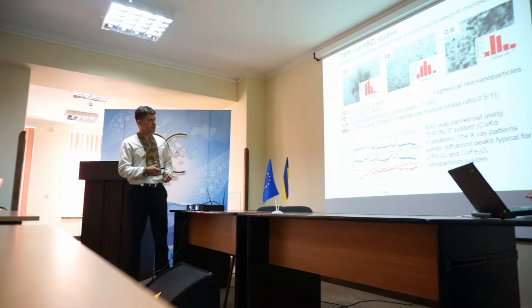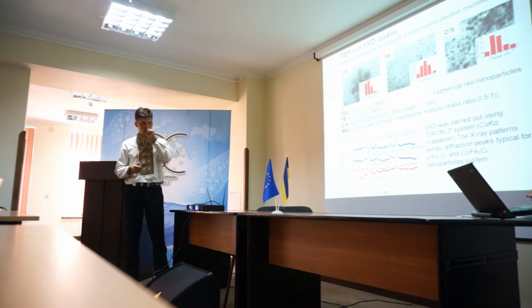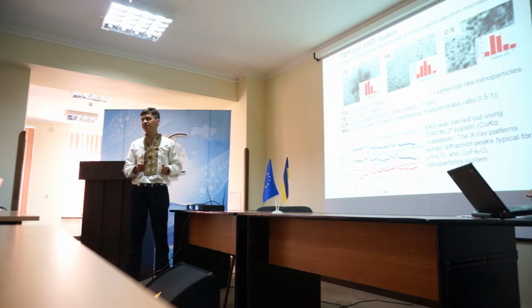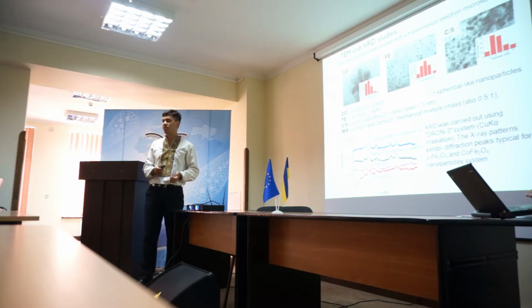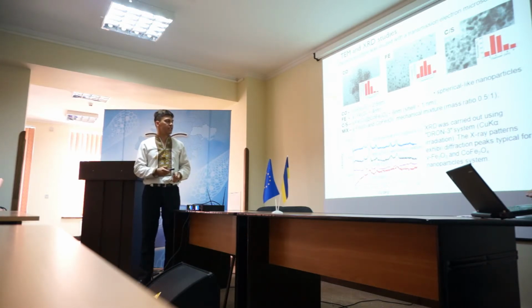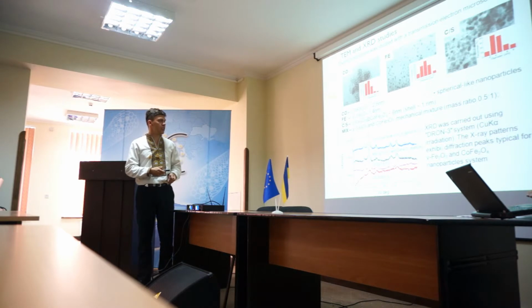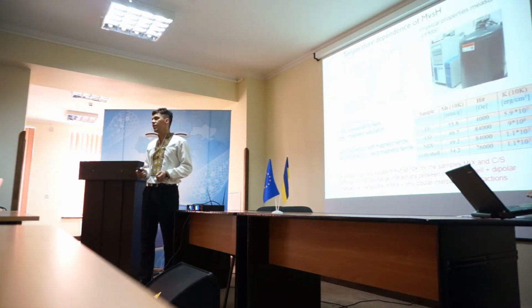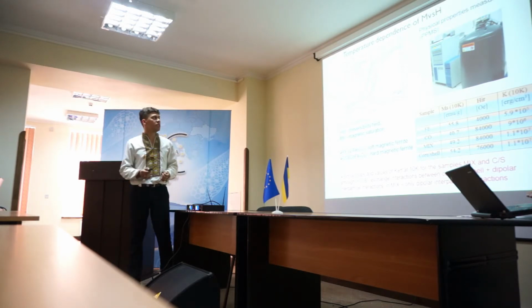The mean size was estimated from the TEM measurements. The nanoparticles are mostly spherical. From XRD measurements, we can see that the nanoparticles are crystalline, and the diffraction peaks are typical for the respective samples. Let's now start talking about the magnetization measurements.